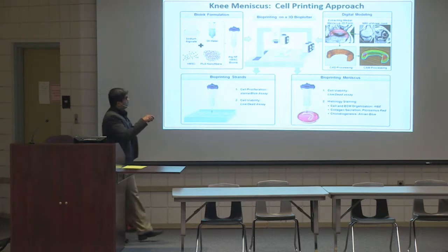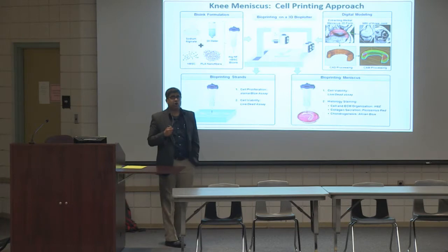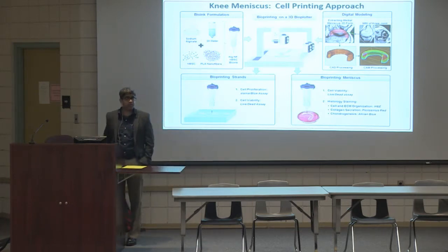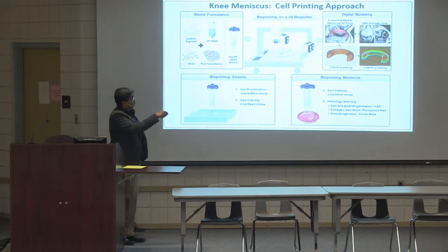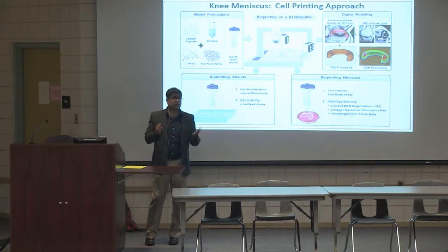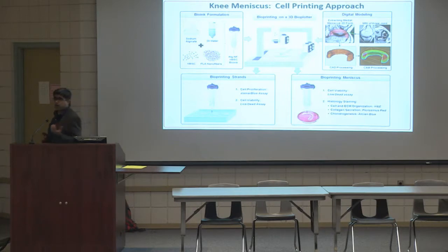On the meniscus side itself, this is where the 3D printing aspect helps. We actually got a scan, an MRI scan of a soccer player who had injured their knee, and through our modeling techniques, we were able to extract it out and then essentially bioprint the whole thing. And then we studied, did the cells survive the process? Because think about it, this is a manufacturing process. You have living cells that you're applying extrusion, air pressure to, and causing them to deposit in a certain way. So we wanted to see if the cells survived.